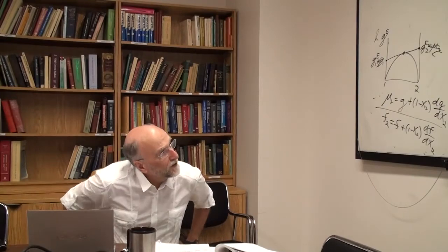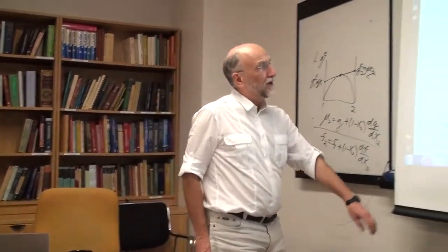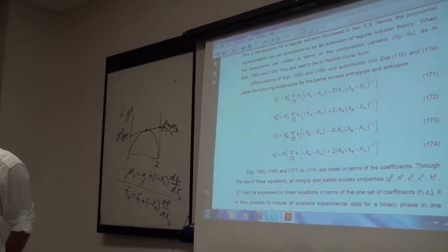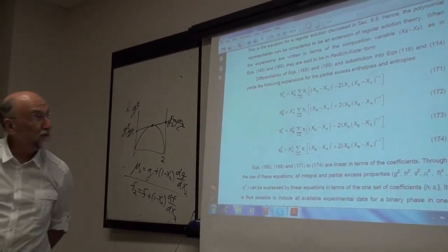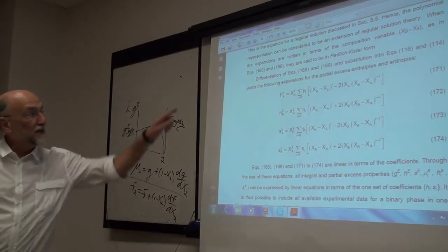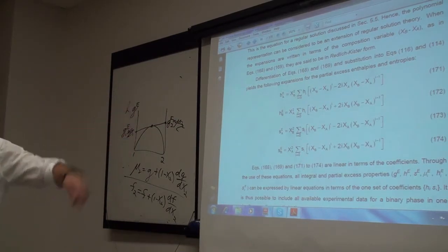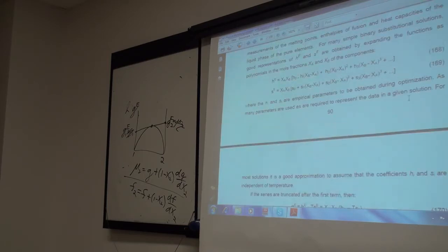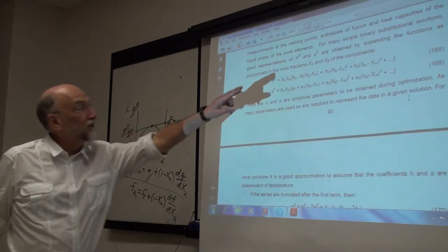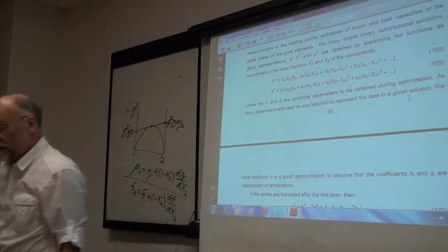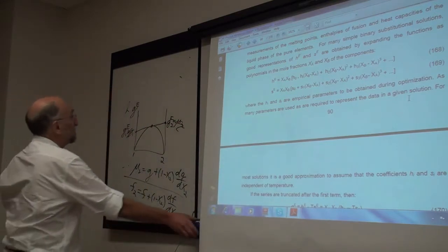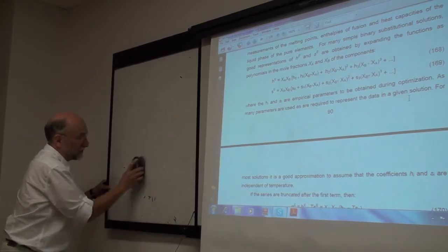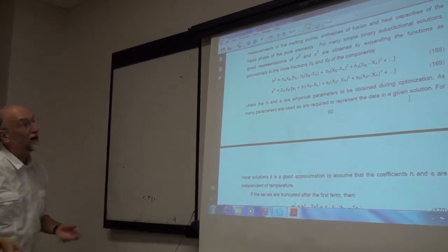Okay, why do we do it this way? We expand it in terms of xb minus xa. Remember xa is 1 minus xb, so you don't need both xa and xb. You could take this expression, let's make it even easier, let's go back to 168. In expression 168, I've done the expansion in terms of xb minus xa. Why? That's called the Redlich-Kister way of doing things. But I can, of course, just use xa equal to 1 minus xb.